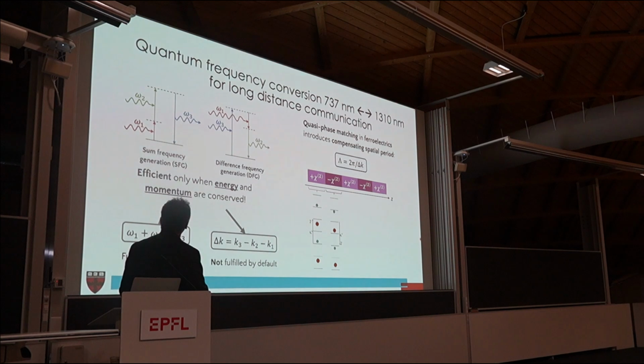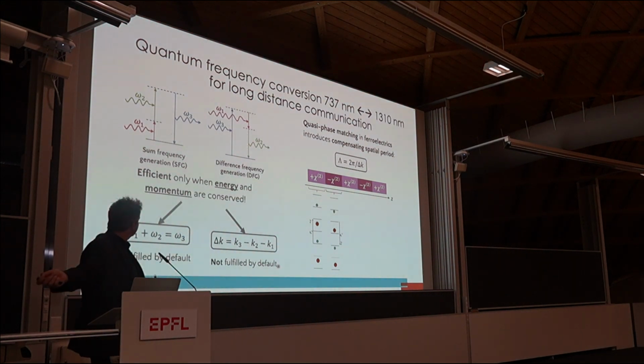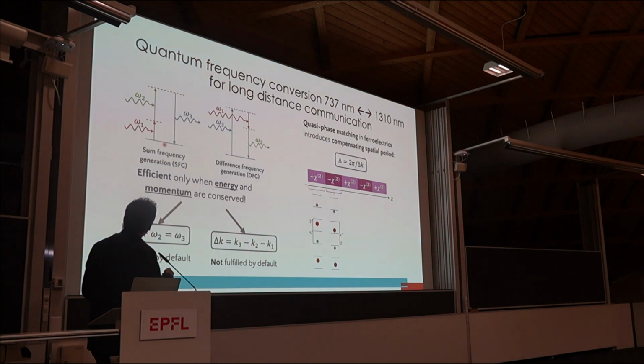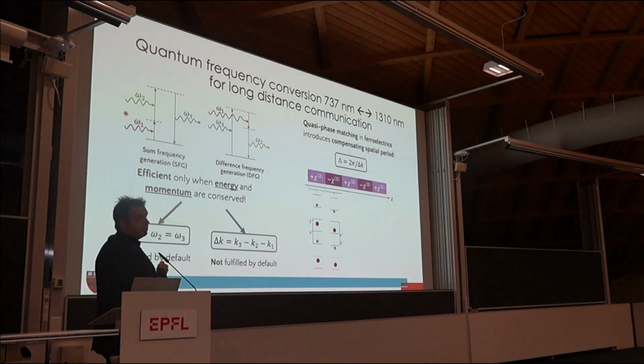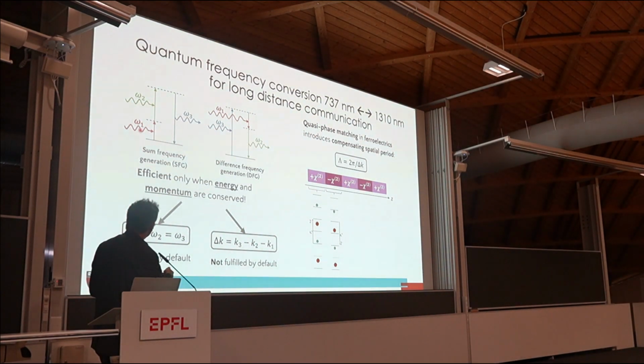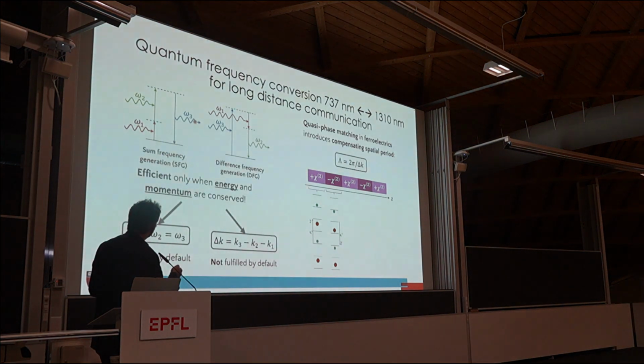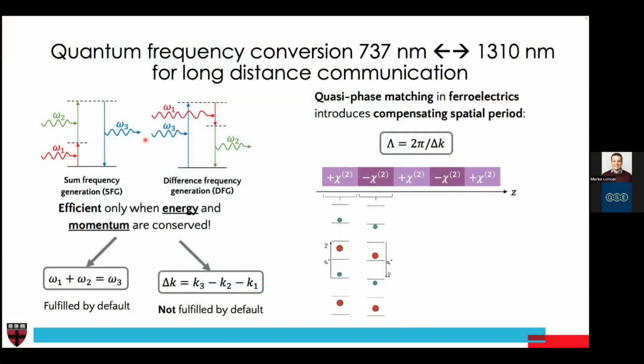We can start with sum frequency generation. We go from 1300, let's say 1300 will be converted to 737 by providing about a 1600 nanometer pump. So we can take the almost 100% conversion from 1300 nanometer to 737 nanometer light. And the other way around, we can go from 737 to 1300 by applying the same pump. This process should be efficient